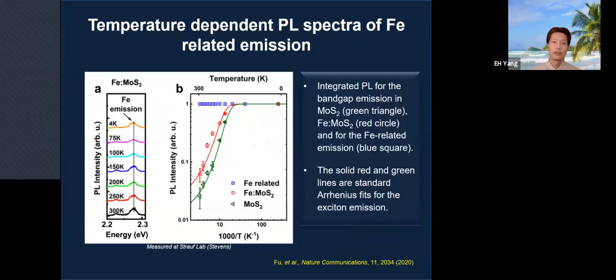Now, another important measurement is photoluminescence spectra. So this is a temperature-dependent photoluminescence spectra. On the right, especially, it shows the integrated photoluminescence for bandgap emission. So you see this bandgap emission in molybdenum sulfide in green triangle, and that of iron-doped molybdenum sulfide in red circle. But you see the strange thing, that is iron-related emission. There is a blue square that is independent of the temperature. Okay. So we scrutinize this iron-related emission here.